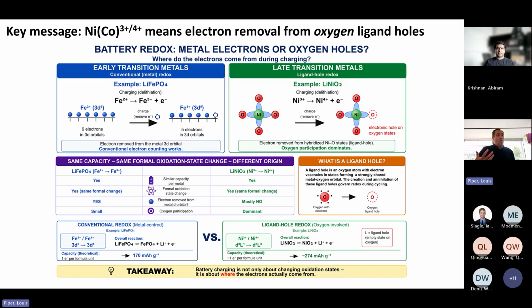But essentially what we point to is you start seeing, even though you are doing nickel 3 plus to nickel 4 plus, a significant contribution of your orbital electron density comes from those which have more oxygen 2p character. This is really important with regards to explaining their behaviors, but it's also providing the groundwork of linking that terminology with how other oxide electronic structure systems exist.